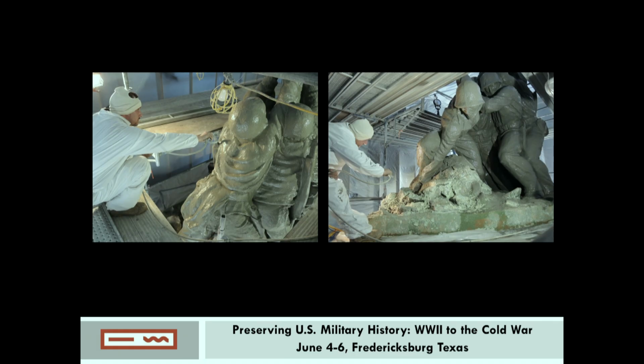Then started the coating sequence. This was complex and numerous coatings were used. The sculpture first dried for a period of 10 days to ensure the maximum cure. And we had to construct an enclosure to do environmental controls for RH and temperature, so the coating sequence could go on in the correct fashion according to the manufacturer's recommendation.